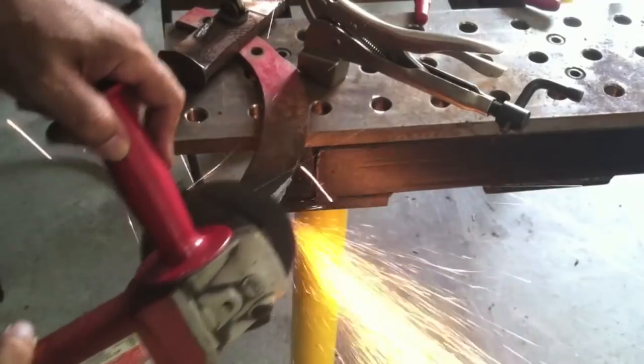We started off doing edge welds, and the practical application was a tiller tine, and I clamped a piece of copper to the back side of it to kind of cast the weld metal, give me something to weld up against, and it didn't stick. Because it's copper and it's so heat conductive that it just takes the heat right out and doesn't melt. And that worked out just fine as far as building up that tiller tine and grinding it off, reshaping it